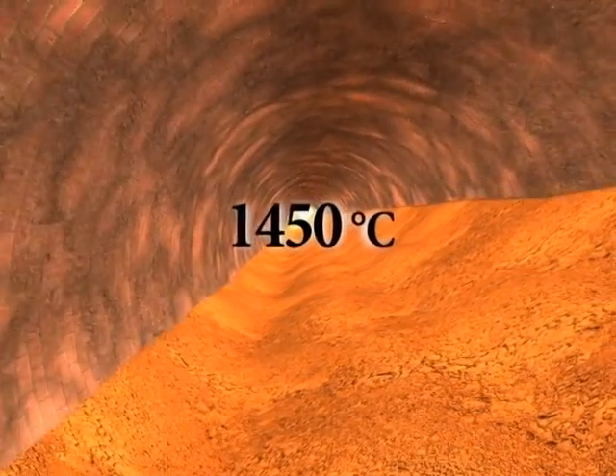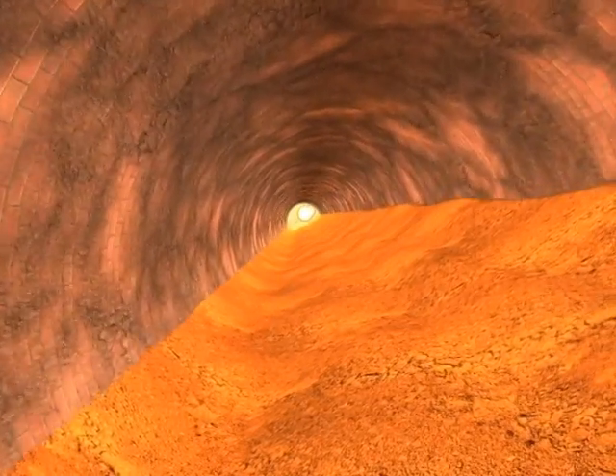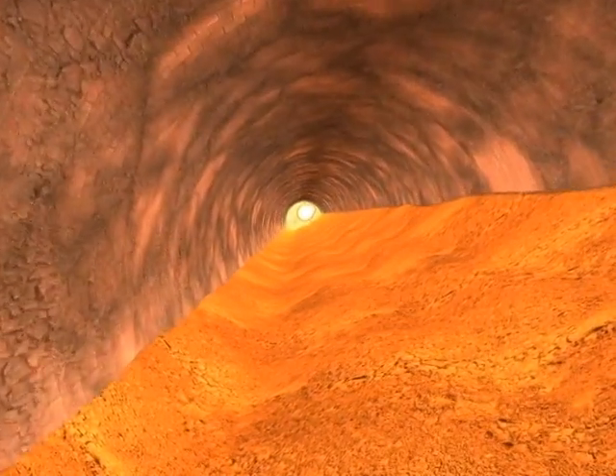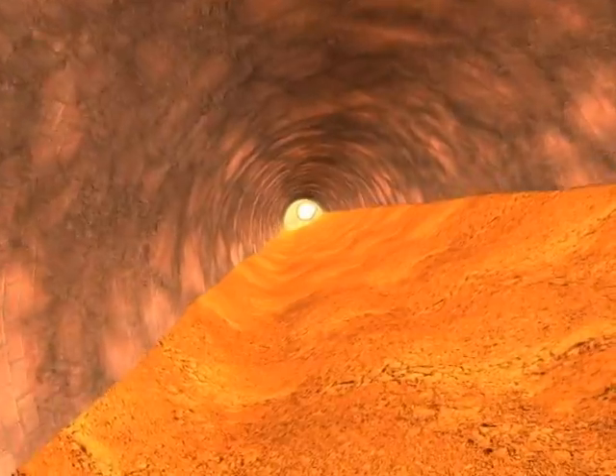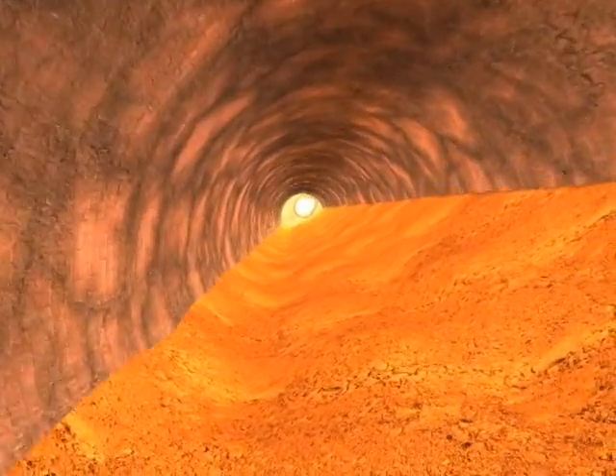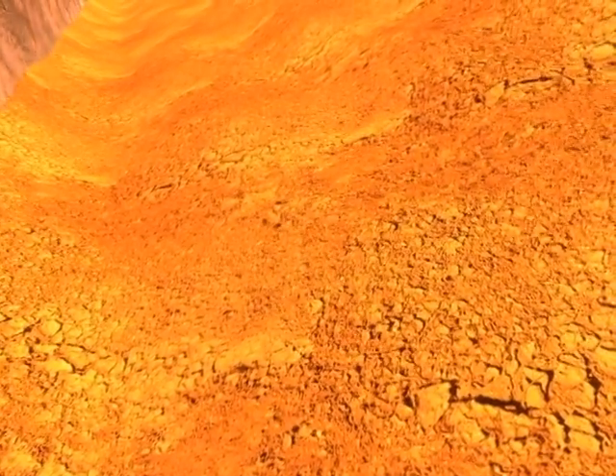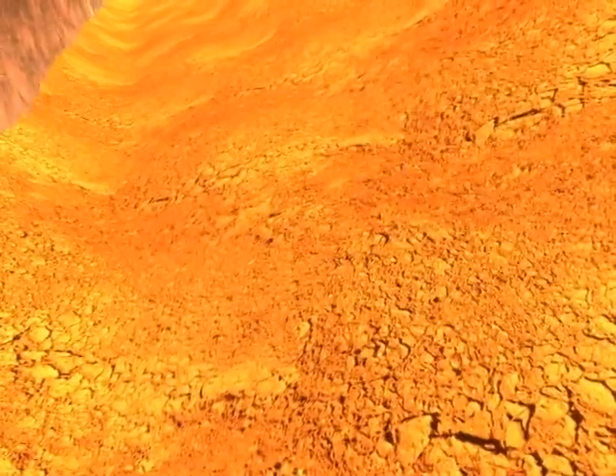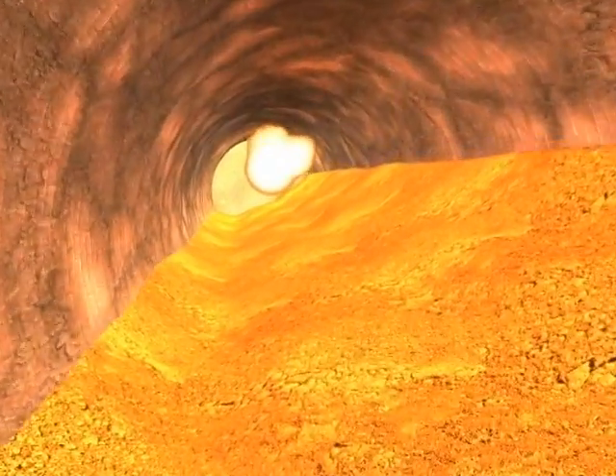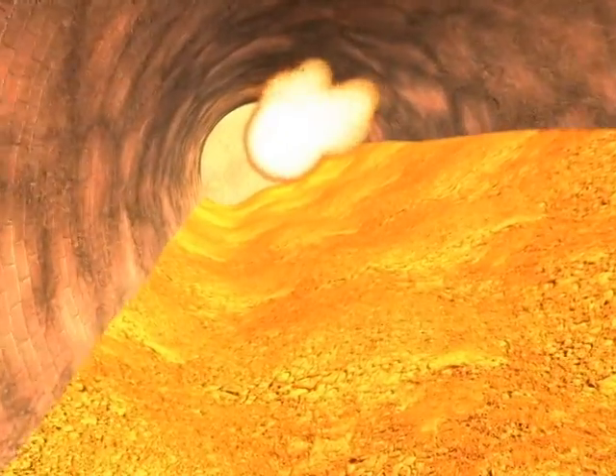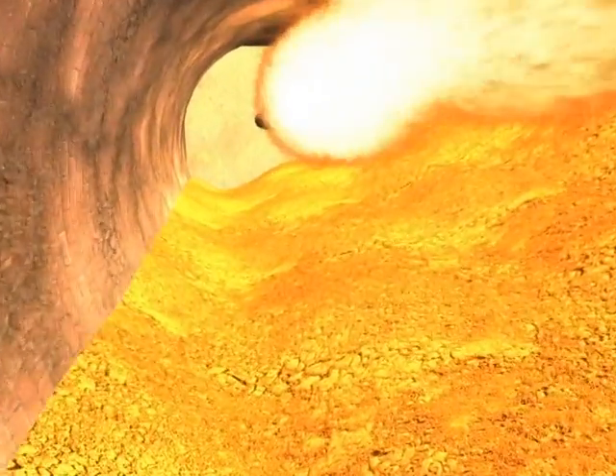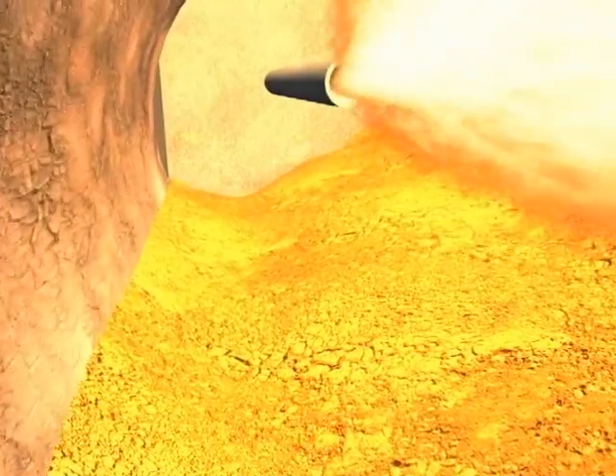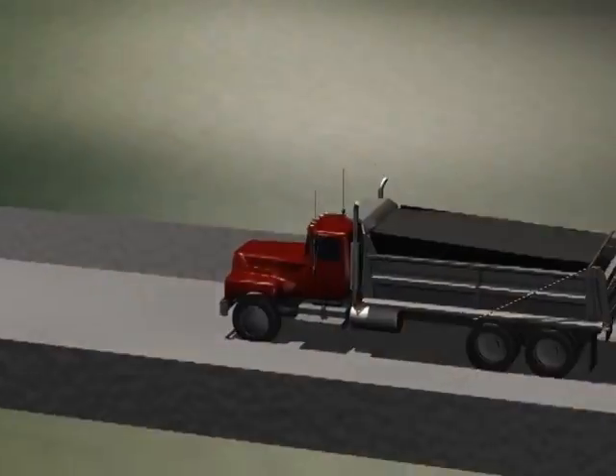The material then travels into the clinkerization or lava zone of the kiln, reaching a temperature of 1450 degrees Celsius. It is at this point the materials form the new compounds, which are required to make cement. The metal and glass-like materials actually melt and draw in the calcium from the limestone to form the clinker compounds. The clinker that forms ranges in size from that of beach sand to the size of golf balls and is red hot. During operation, the kiln is fired using a combination of fuels to provide the extreme temperatures required to convert the kiln feed into clinker.